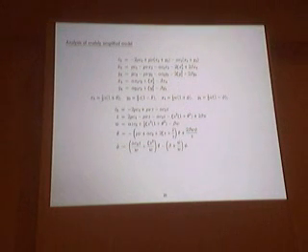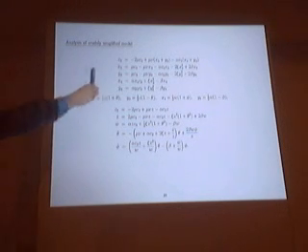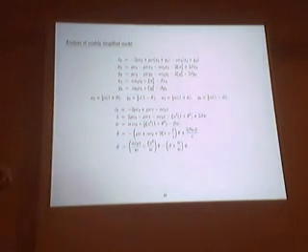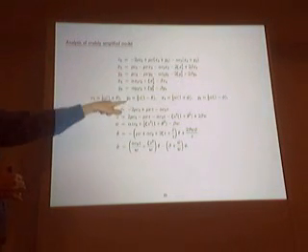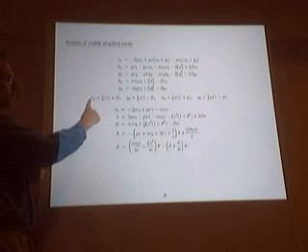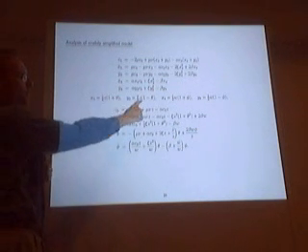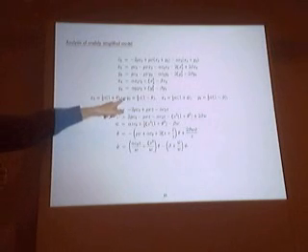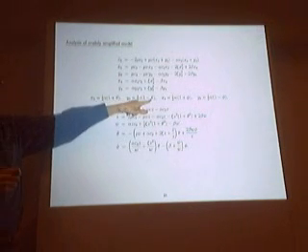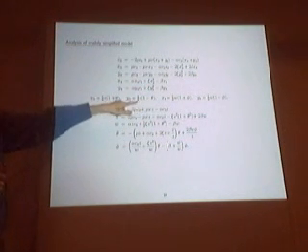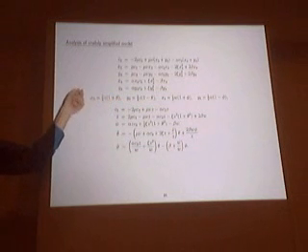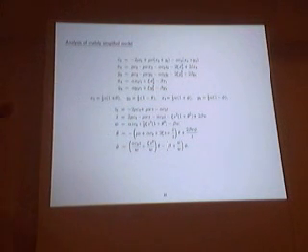So try to understand why doesn't this quite work? Can we do anything about it to correct it? So that's the system of equations. I'm not actually going to try and solve these, but one way of analysing them just to see what happens is, instead of thinking about the concentrations of left and right, think about the total. To write the concentrations as an average concentration Z, and then theta is an enantiomeric excess. So one of the concentrations is this term 1 plus theta, the other is 1 minus theta. So when you add these two together, you just get Z, and you take the difference, you get Z times theta.